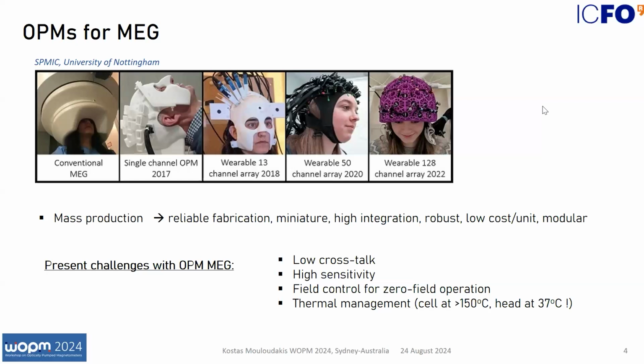And mass production is really a big challenge because we need reliable fabrication of miniature sensors and automated and rapid assembly at the wafer scale, high integration with robust technology, low cost, etc. But there are also engineering challenges like low crosstalk between different sensors. Each sensor has to have high sensitivity. We need to operate at zero field to increase our dynamic range, but also thermal management is a big issue because each sensor should operate at temperatures higher than 150 degrees.